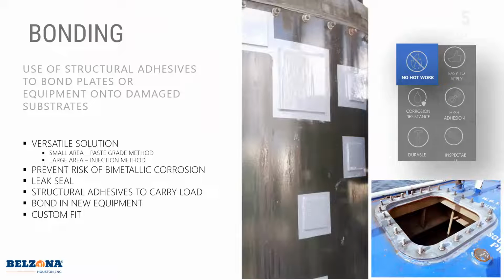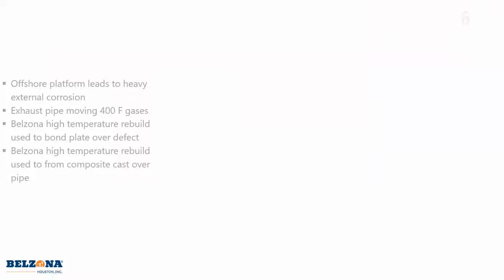substrates as well. Now, these same materials can be used in what we call plate bonding, which, when people see this and they're not familiar with Belzona, is really a unique and believe it or not type of application. Instead of welding, doing a lap weld patch, or even welding in new equipment like this hatch on this flange on a ship here, we can bond them in with those same rebuilding materials, and they are going to be adhered solidly to the substrate. Like I said before, 3,000 to 5,000 PSI adhesion, these plates are not coming off. When done correctly, this full flange is bonded down, so the full adhesion is going to give you the same strength as a weld around the edge. And you can do it in scenarios where you might not be able to do hot work. So definitely versatile, and that's what allows us to do these applications that can sometimes wow people.